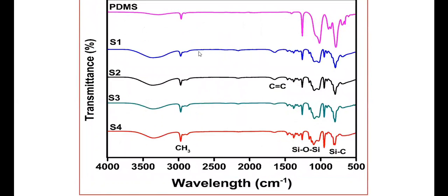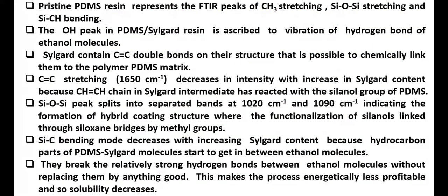So this is Fourier transform infrared spectroscopy. Over here, the pristine PDMS represents FTIR peaks of CH3 stretching, Si-O-Si stretching, and Si-CH3 bending. And the OH peak in PDMS-Sylgard is associated with vibration of hydrogen bonded ethanol molecules. So Sylgard contains C=C double bonds in its structure that can chemically react with the polymer of the PDMS matrix.